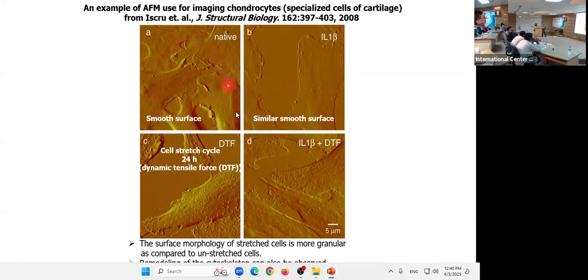They looked at the baseline condition. These cells are cultured in the baseline conditions. The atomic force microscopy showed a very smooth surface of these cells. They treated the cells with IL-1 beta, which will activate the gene expression in these cells, and they made observations on the topography or the cell surface of the receptors. And they also stretched the cells for 24 hours on this rubber substrate.